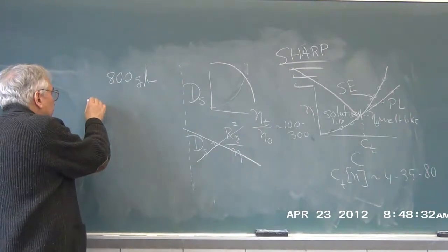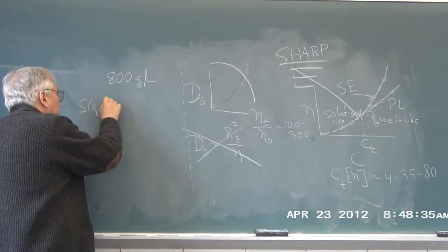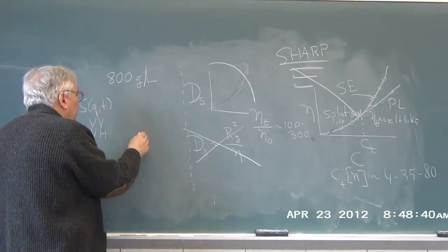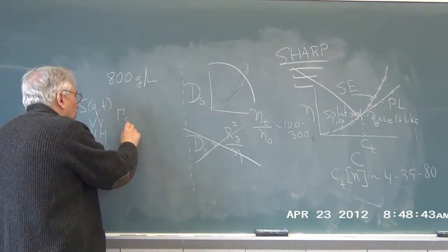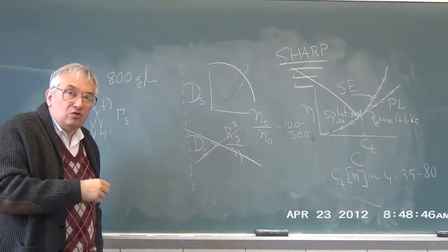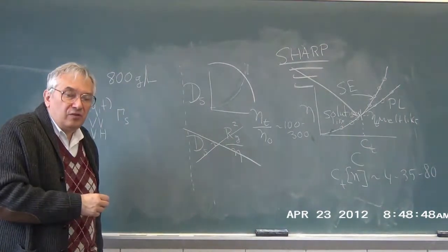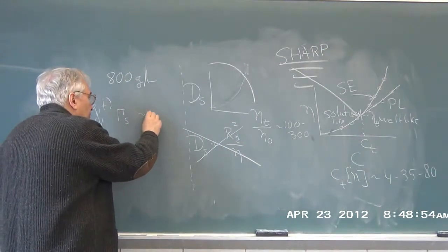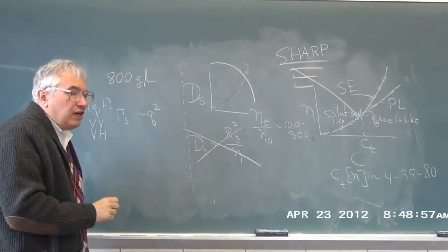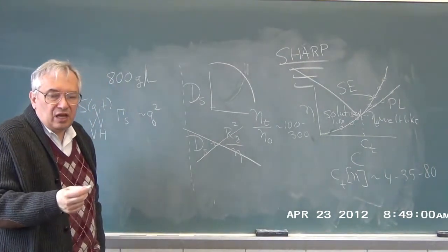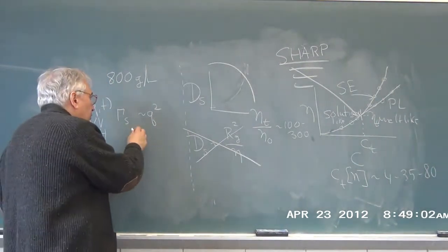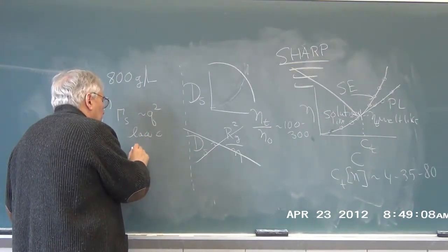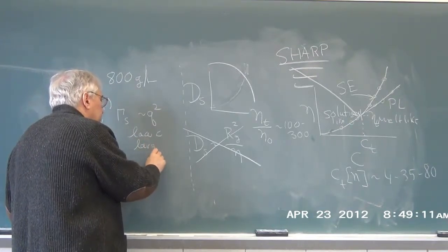And the core issue is that if you look at the light scattering, and there are also experiments that look at both VV and VH scattering, you see a slow mode. And the slow mode slows down as you increase the polymer concentration. However, there is another feature, which is that the slow mode depends on scattering vector squared. It depends on scattering vector squared if you are at smaller concentration or larger temperature.